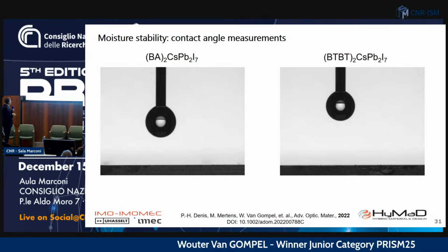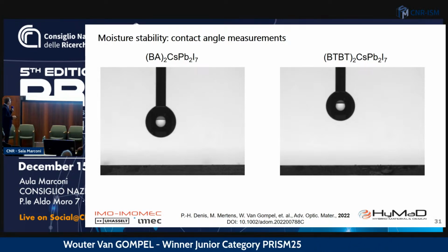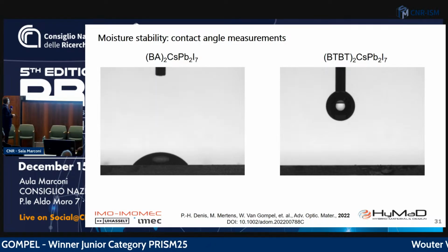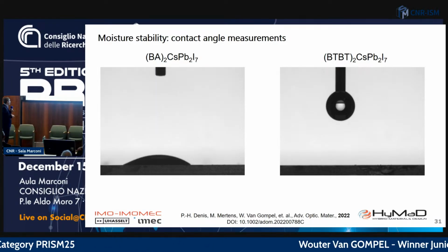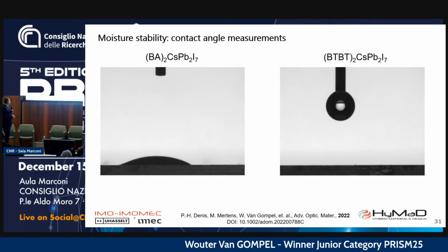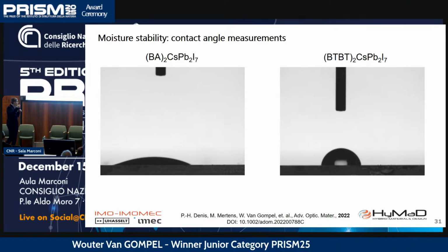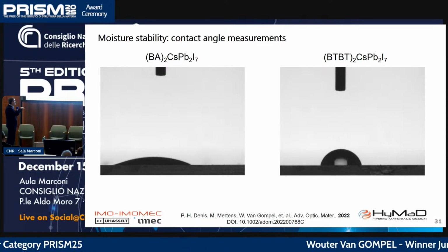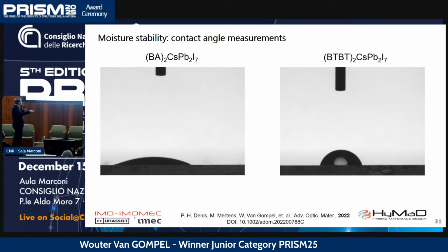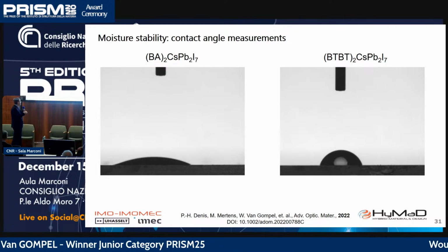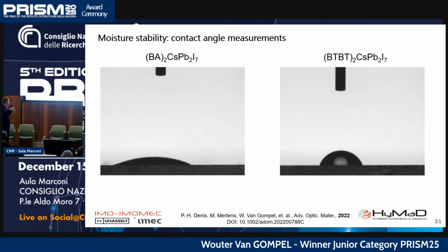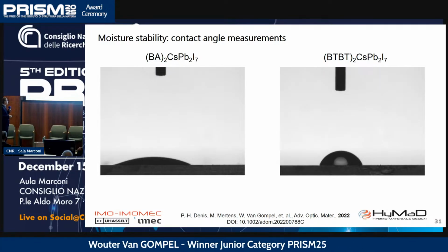And if you look at the simple contact angle measurement, so just a drop of water on top of this film, you see with the reference that the drop spreads out immediately. So it's a very hydrophilic surface. It degrades the material underneath even. While with this BTBT, it just stays on the surface with a quite high contact angle, which means that actually the surface has become hydrophobic. And we hypothesize that these BTBT molecules terminate the perovskite surface. They are at the air interface and protect the inorganic framework underneath. And this is the reason why they are so resistant to moisture from the air, because they actually repel water, which is a quite special case for these perovskites.